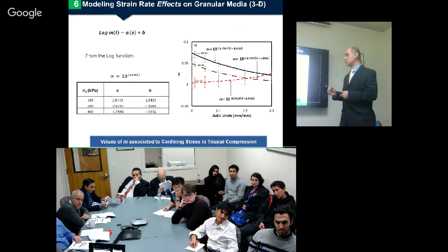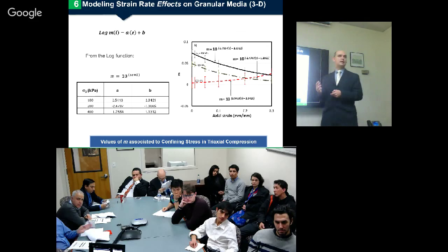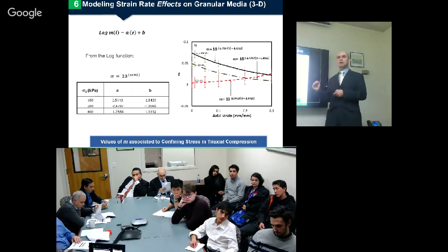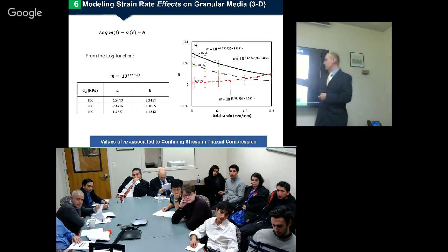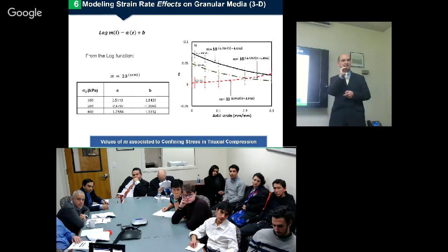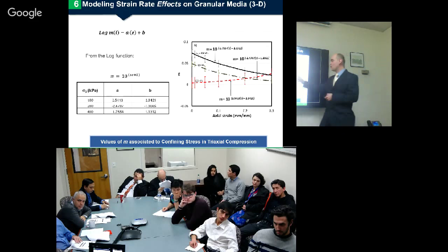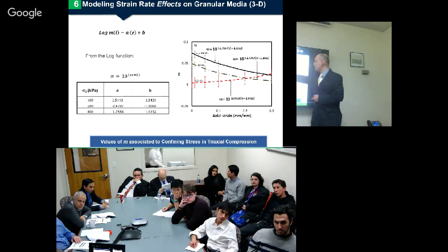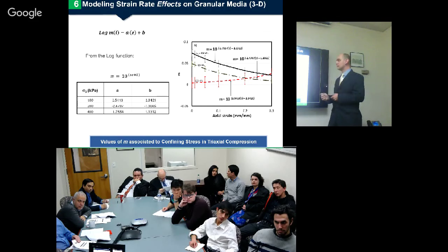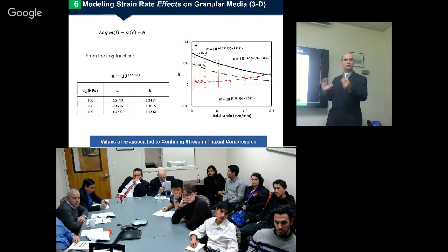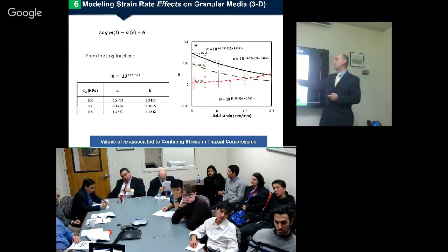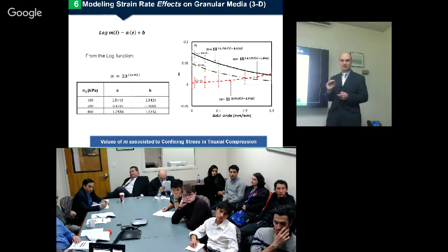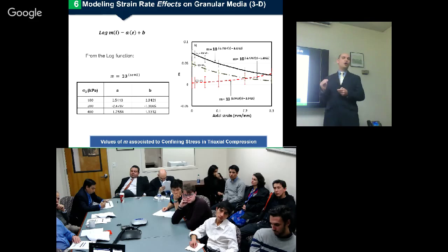And that can also be seen in this figure when getting rid of the log function. The red line here is the behavior of the material loaded at very low confinement, 100, and it increases, going up and up for 200, and it's much higher at 400. Ideally, based on what I saw with all of this analysis, for material, especially for sand,